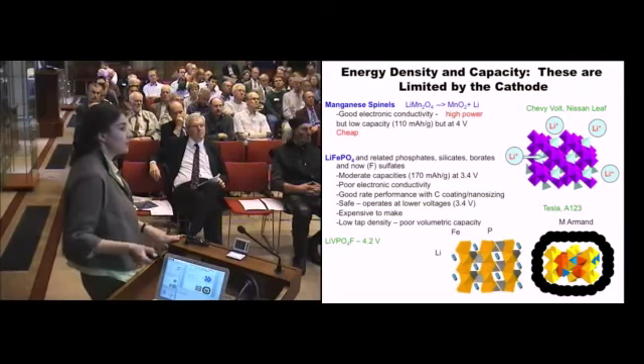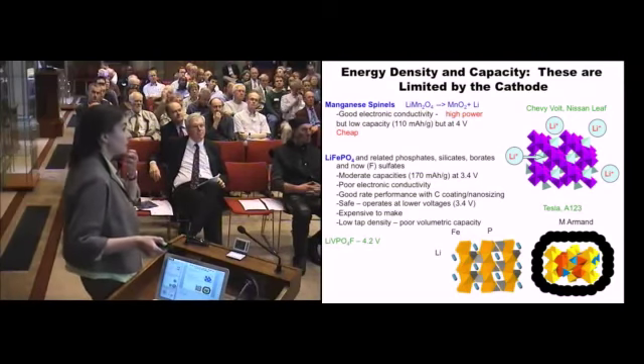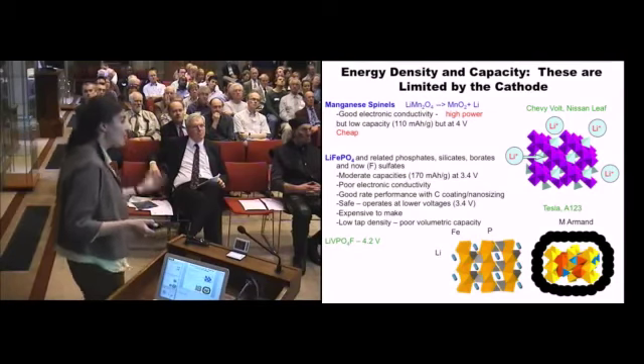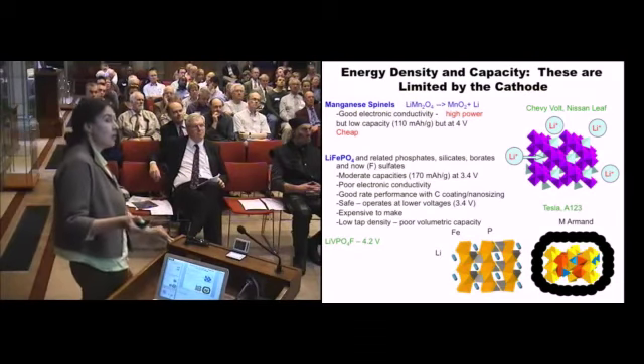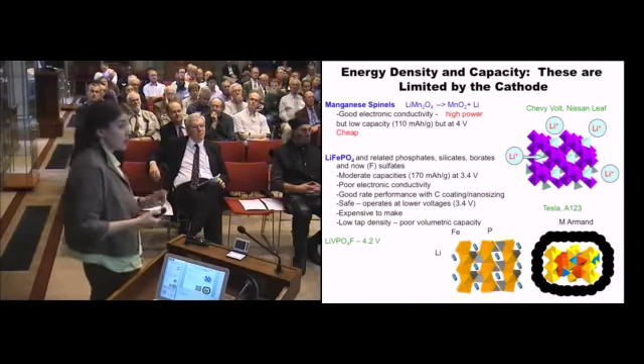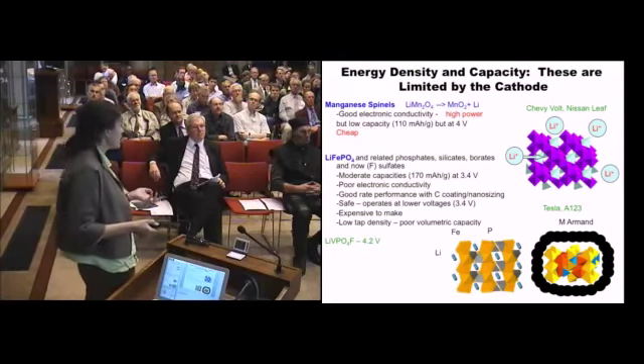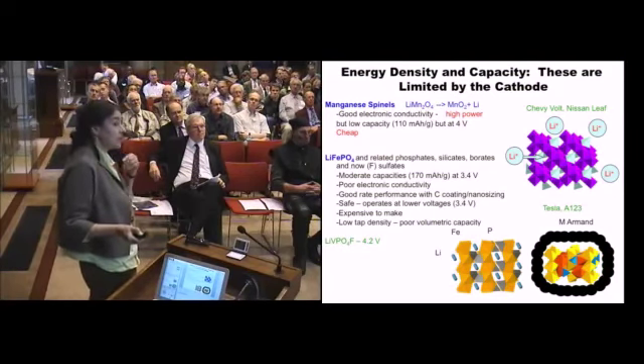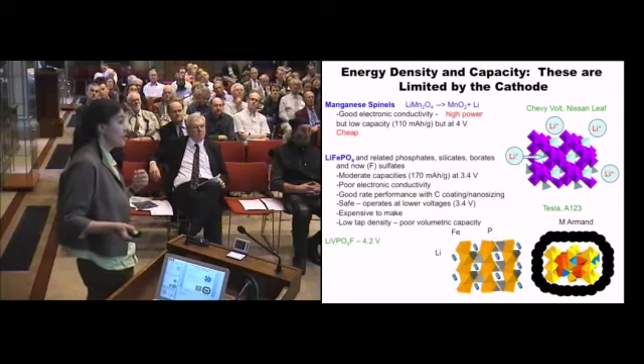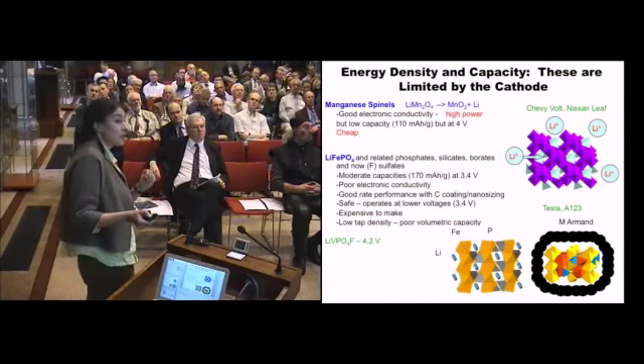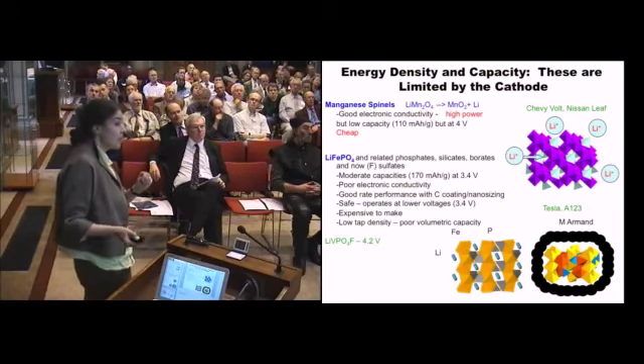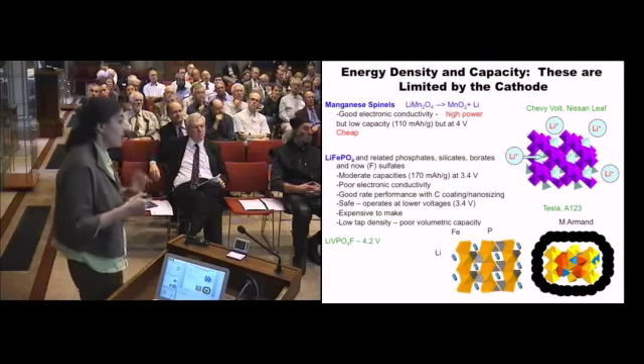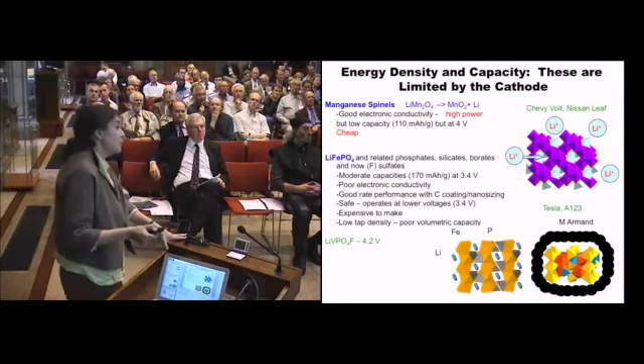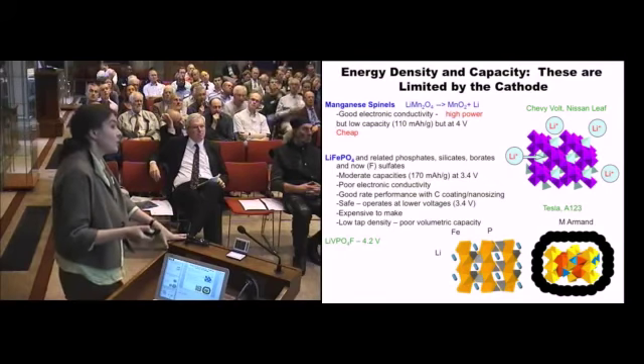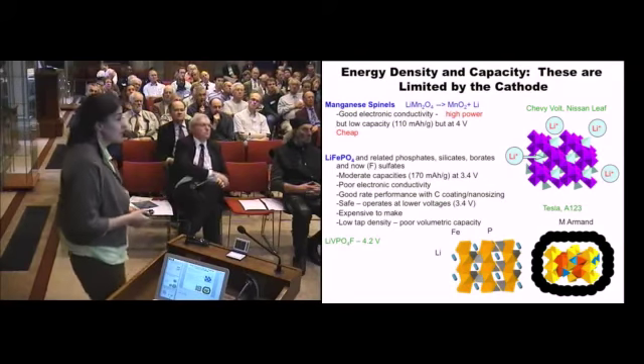It's a totally different structure with lithiums now in one-dimensional tunnels. And in the late 90s, he'd got reasonable performance. But Michel Armand, 5 years later, he realized that if you nanosized it, so you made small particles, and you covered it with a coating of carbon, you could then find ways to get electrons in and out of this insulating material. So if you make it small, the electrons have to travel over less distance, and if you cover it with carbon, you increase the contacts with the carbon particles that you're putting into the composite structure. And so he showed you can get very good rate performance from this thing.